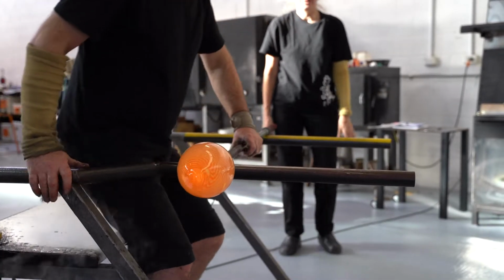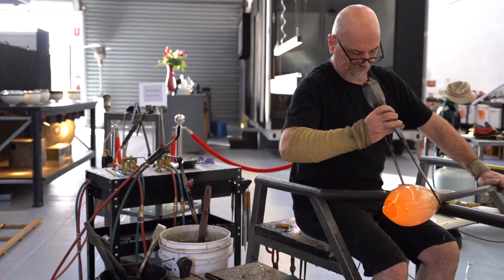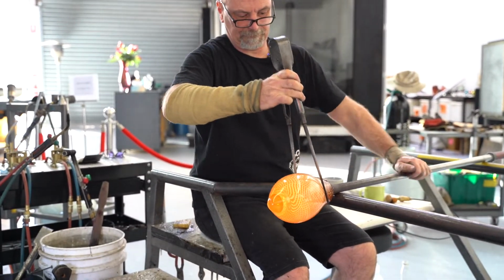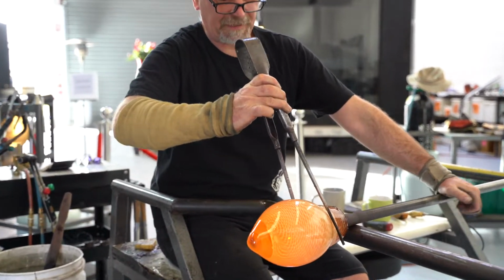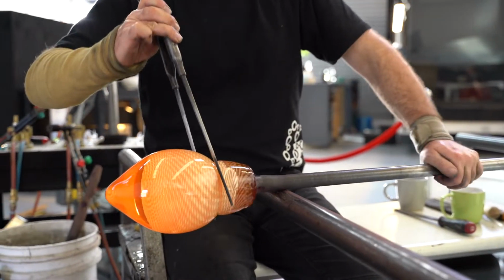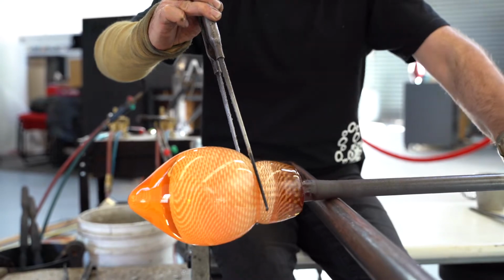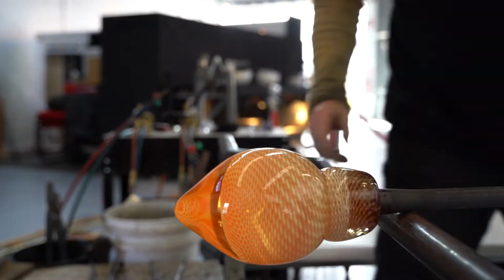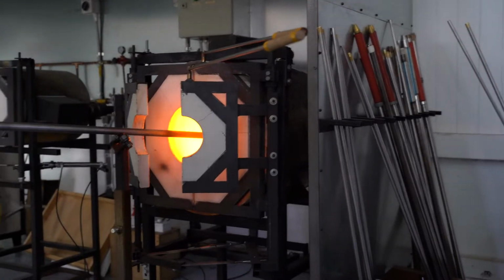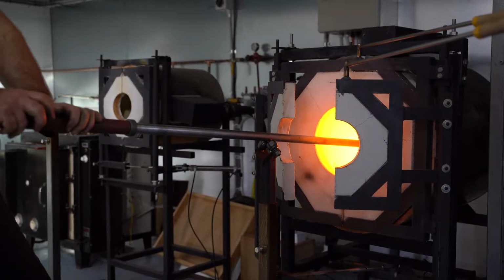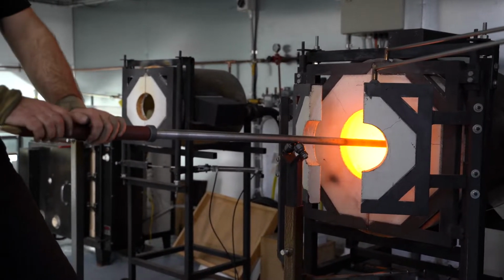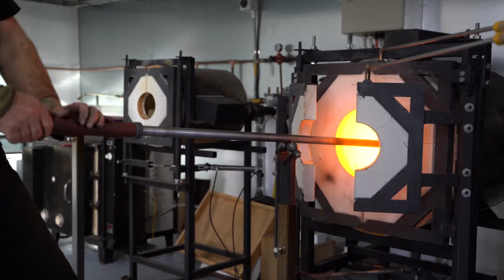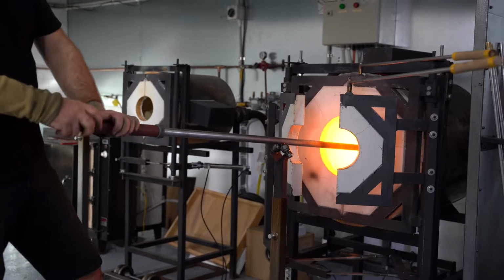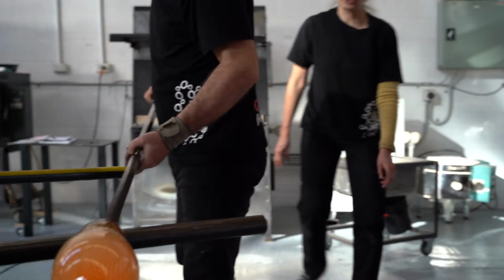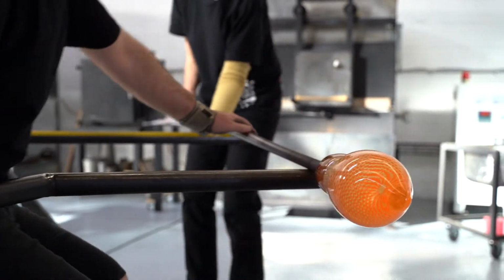So what we're really doing when we're blowing glass is managing the malleability. Glass as a material at about 1200 degrees is a very honey sort of consistency, all the way down to 600 degrees where the glass is pretty much rigid and solid. But all through that 600 degree range the glass becomes softer and softer the hotter and hotter it gets. And the actual blowing process is all about managing the viscosity of the glass. Sometimes we're heating the whole piece, sometimes we're heating very specific parts of it, just depending on what part of that process is. But the whole process is understanding and managing the malleability of that glass.